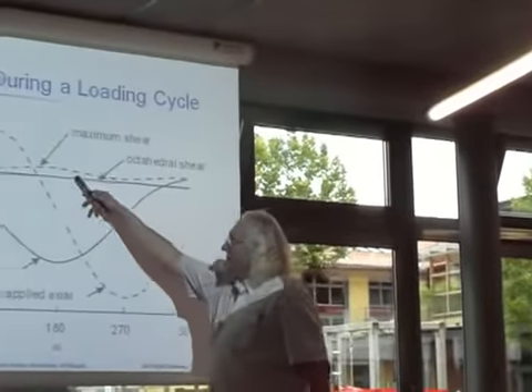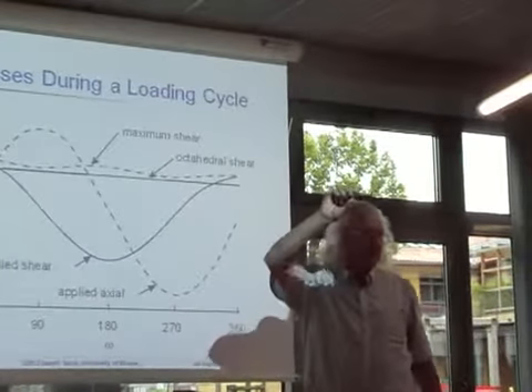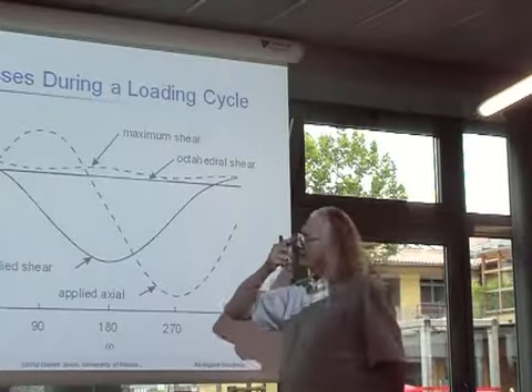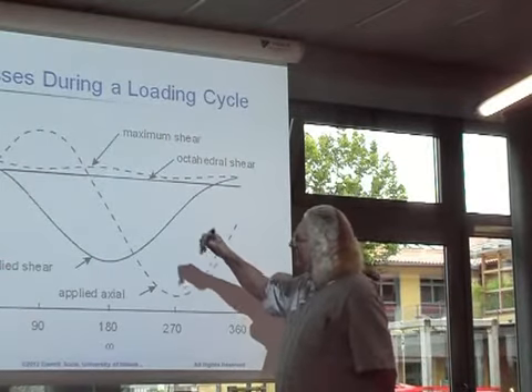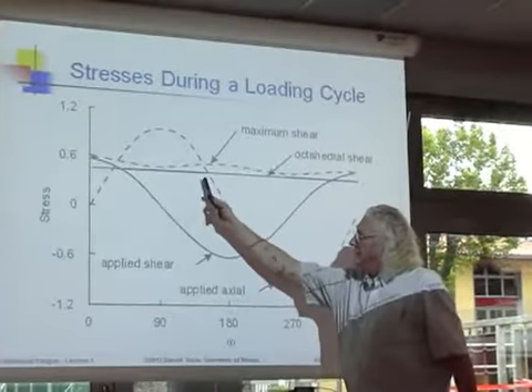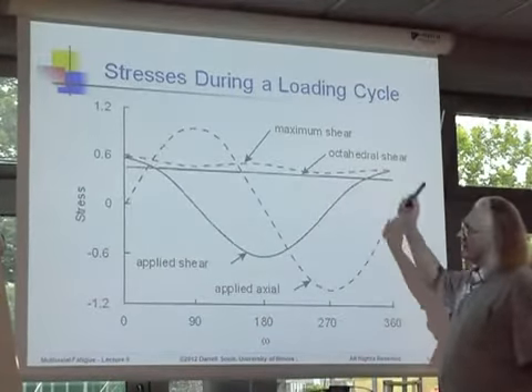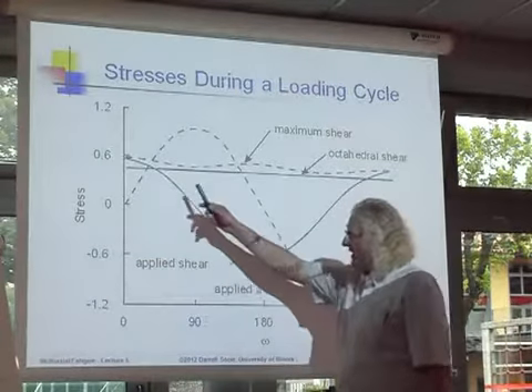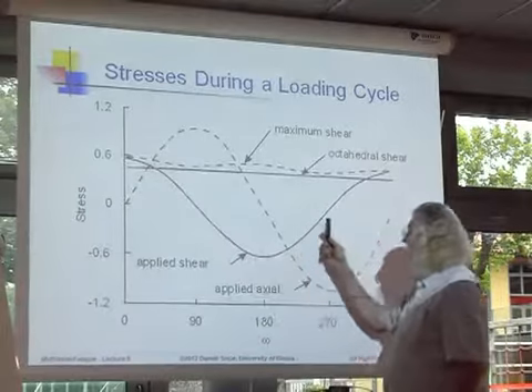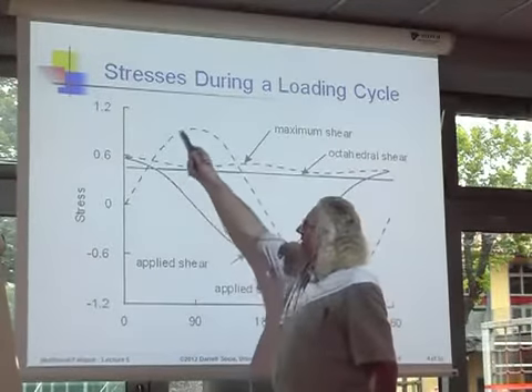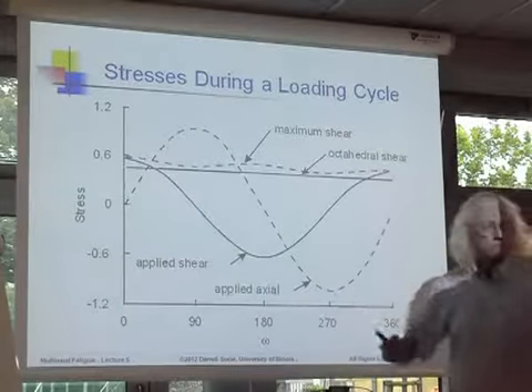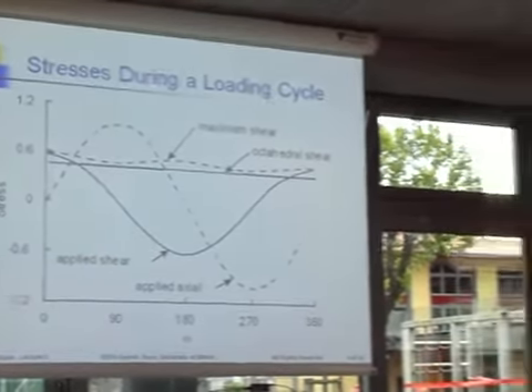The maximum shear stress changes a little bit, but not too much. It rotates in direction, but its magnitude never changes. If I altered the ratio of torsion to tension loads, I could make the maximum shear stress constant, and the octahedral stress would have a small sine wave. But look, there's a big change in the applied axial loads and a big change in the applied torsion load. The octahedral parts are zero. And this has been the problem in non-proportional loading. Many of the traditional models simply don't work because they use equivalent stress, which is not sensitive to the out-of-phase loading.